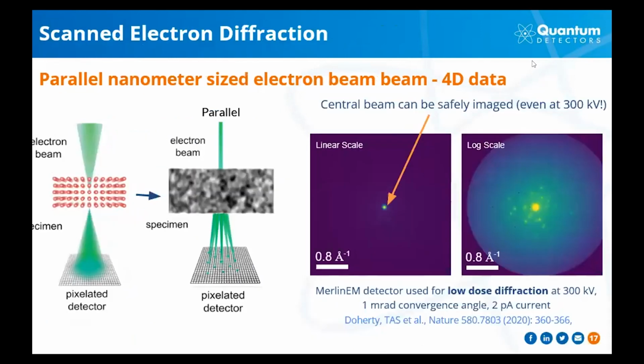As I mentioned before, Merlin is capable of imaging high-intensity beams together with low electron counts within the same frame, and therefore it's rather suitable for diffraction imaging. And so in this case, we image the sample with a parallel probe, so it's not convergent, it was close to parallel probe, and we can again collect a 2D image of each probe position and hence get four-dimensional data.